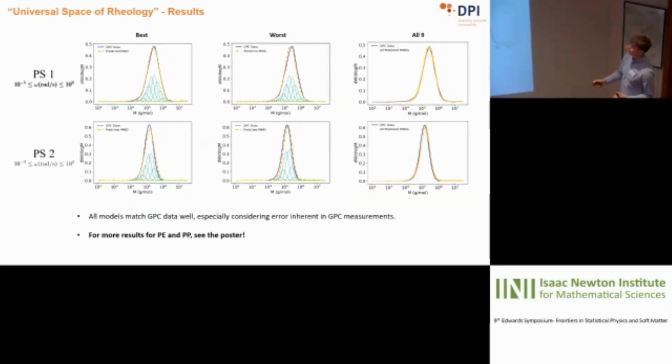So these are two polystyrene polydispersed commercial polymers, and we train 9 neural networks. The training isn't deterministic, so you train multiple and see how consistent your results are. And we get a good estimation of the weight average molecular weight and the polydispersity.